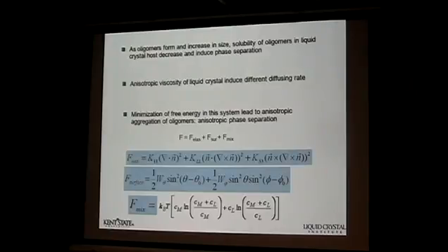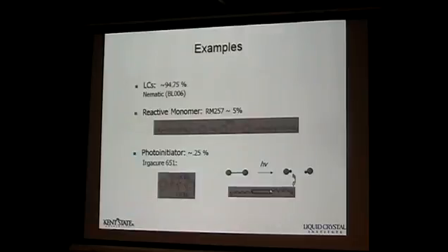Before you use the external energy to induce this phase separation, there is also premature phase separation. So that's a kind of factor you need to consider. The others in the free energy are the anchoring energies, the polar anchoring energy and also the azimuthal anchoring energy, determined by your manufacturing process. Did you rub it strong enough, creating groove structures with periodicity small enough to make sure of the deviation of the orientation of your directors? The director in the plane did not interfere, because of the cell gap effect. And then the tilting angles, the deviation of that, from the first layer up following the pre-tilts of the surface. So I guess something like that is what we were looking for.